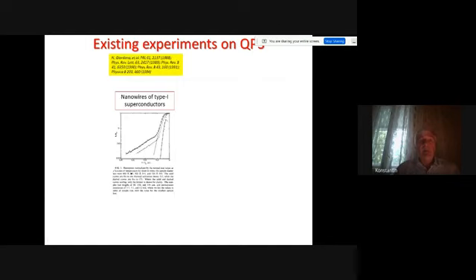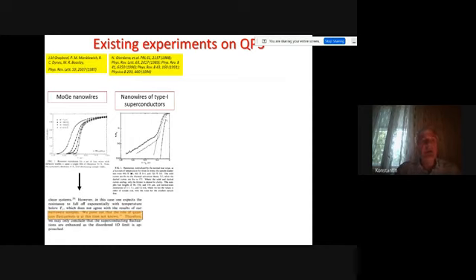So first experiments on this subject appeared in the early 90s and are mainly attributed to Nicola Giordano, who studied several nanostructures made of indium and noticed that there are so-called low temperature tails, which are attributed to quantum fluctuations. But more precise search in literature shows that already a year earlier, in the same group where he did his PhD, a group of Danes already observed such tails at the bottom of the transition and noted that the role of quantum fluctuations at this time is not known.